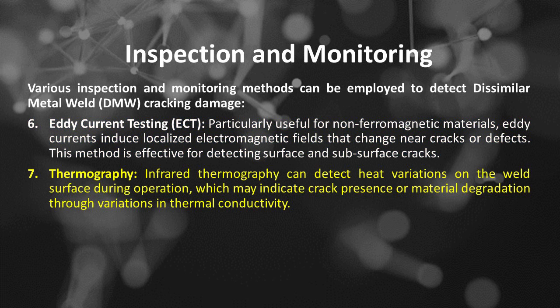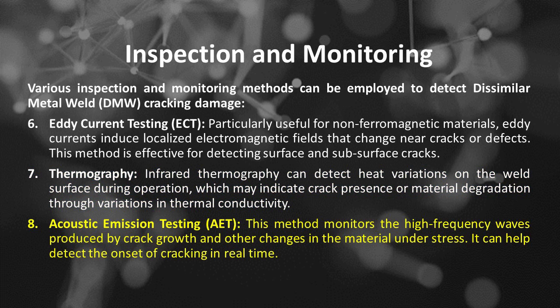Number 7 is thermography. Infrared thermography can detect heat variations on the weld surface during operation, which may indicate crack presence or material degradation through variations in thermal conductivity. Number 8 is acoustic emission testing, or AET. This method monitors the high-frequency waves produced by crack growth and other changes in the material under stress. It can help detect the onset of cracking in real time.